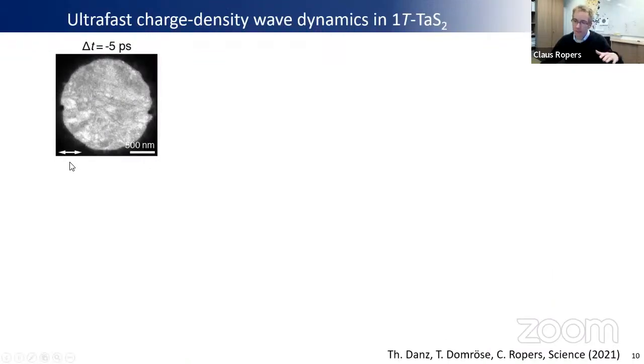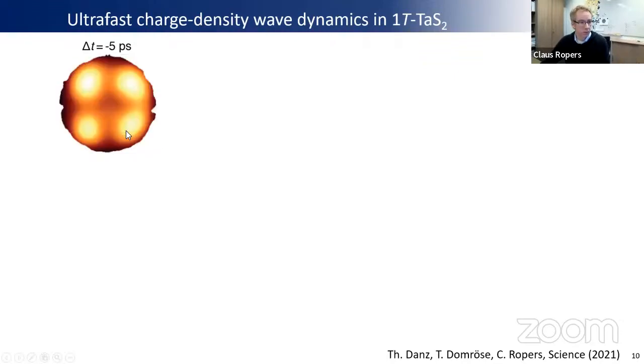This is now again with this mask inserted. So this is before the optical excitation at negative delay times. The image intensity, the dark field image intensity, is a measure of the strength of the lattice distortion as a function of space in this material.